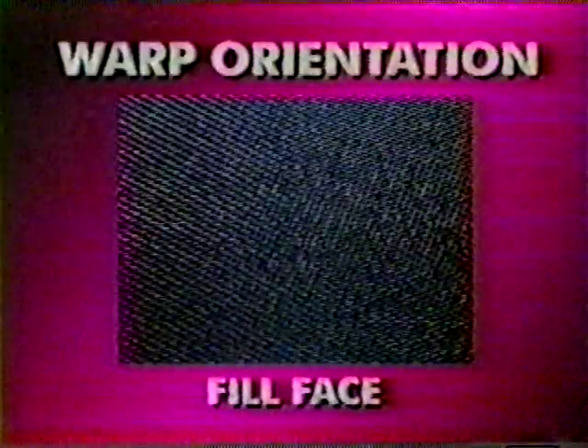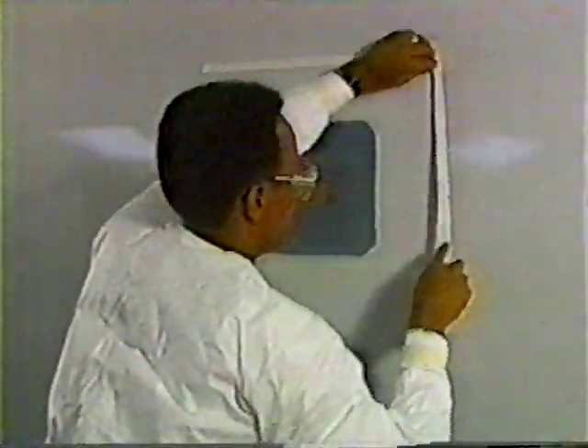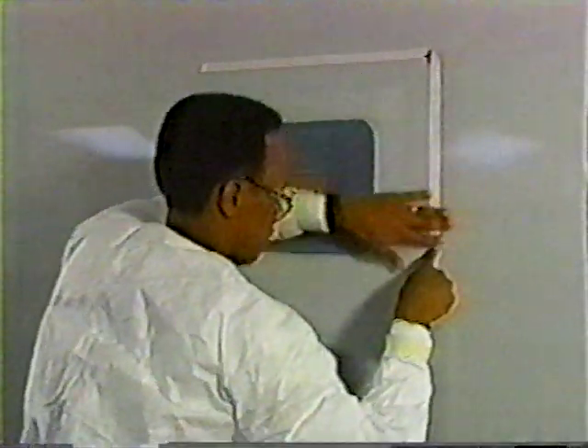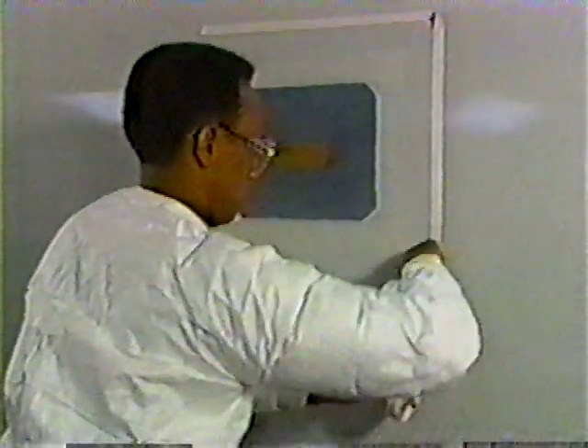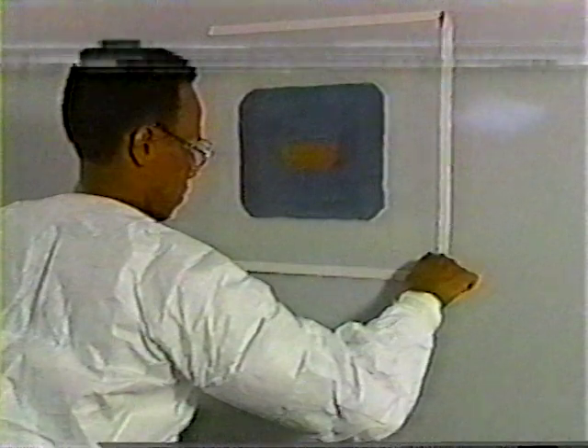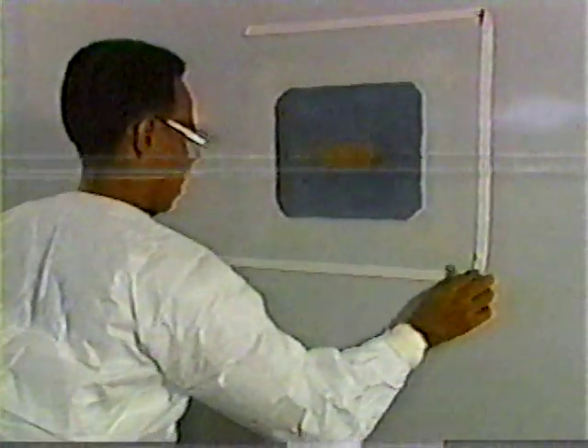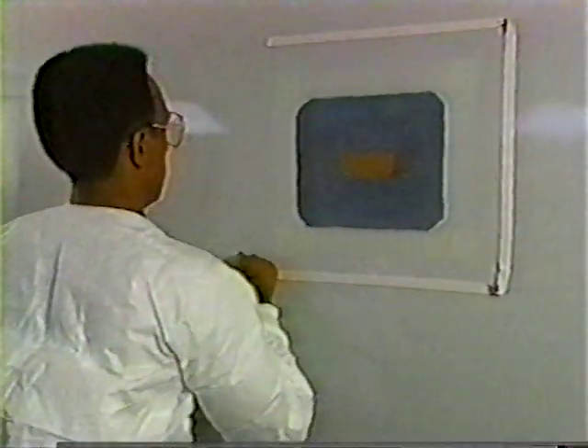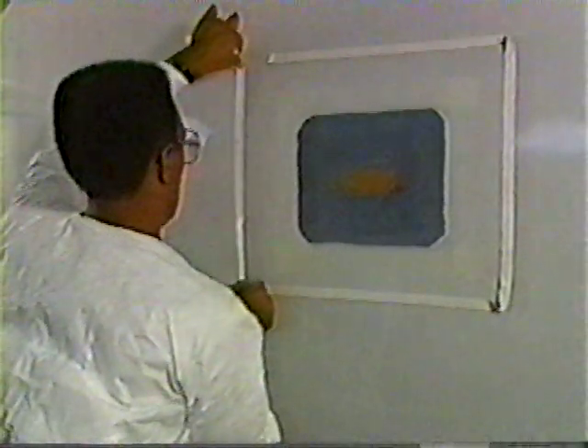Other manufacturers provide yellow Kevlar tracer strands 3 inches apart on the warp face only, and no Kevlar strands on the fill face of the material. To begin the final phase of the repair, apply a strip of sealant tape around the entire repair area, slightly more than 2 inches beyond where the edge of the heating blanket will be located.